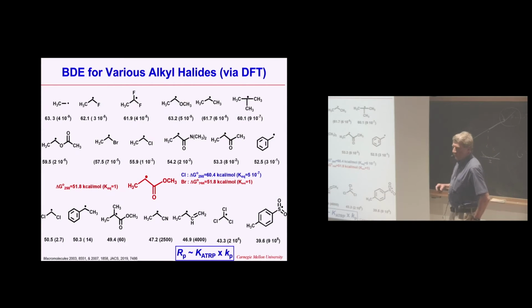So by using DFT or some ab initio calculations, you can measure the bond dissociation energy between this carbon and bromine, or what would be the stability of a radical formed. And these are really spanning many orders of magnitude. So if you look here, for the acrylates, this would be styrene, this would be methacrylates, this would be acrylonitrile, vinyl acetate, or even ethylene.